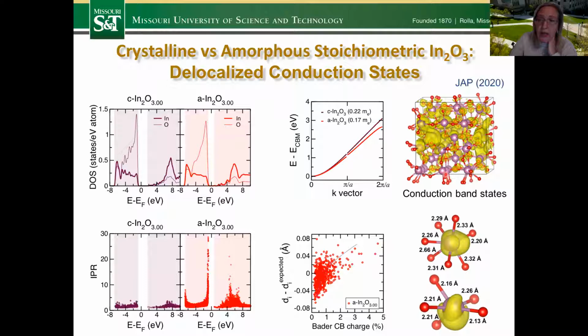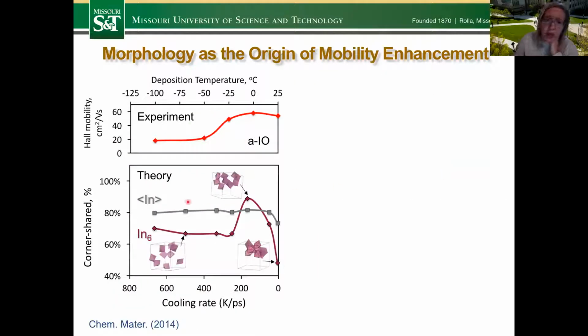And what we found is that those atoms form so-called chains just near the onset of the mobility. So here again, I'm plotting the experimental mobility. This is the same peak as I just showed, but zoomed into the closer range of temperatures near the transition itself. At the same time, I'm plotting the cooling rates, and we are confident that we can put these scales together, the experimental deposition temperature scale and the theoretical molecular dynamics cooling rate, because we made those scales based on the structural comparison between experiment and theory.